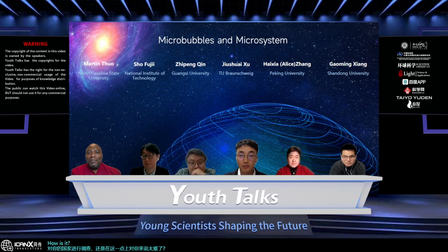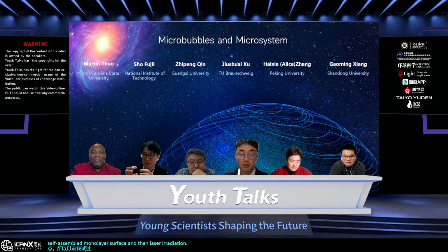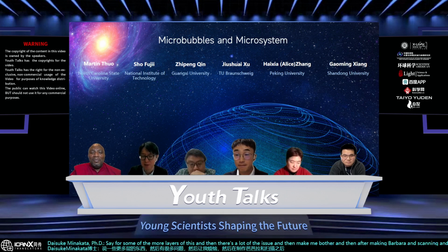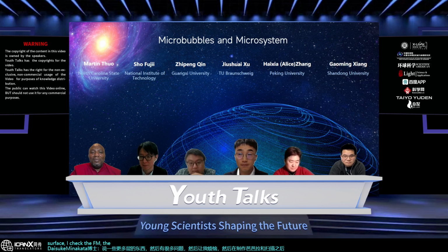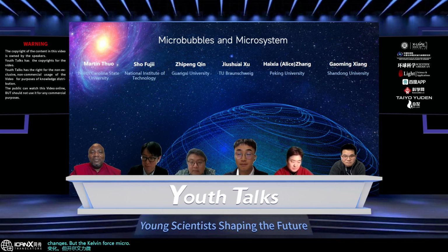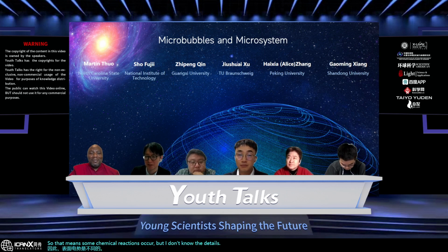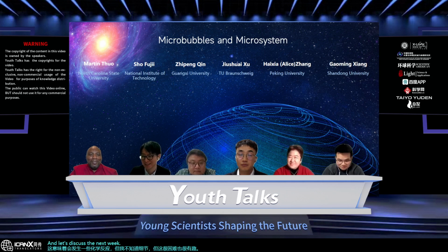It's a very good point. Previously I tried a self-assembled monolayer surface, then irradiation and making a bubble, and then after making the bubble and scanning the substrate surface, I checked with AFM and saw no topological changes. But with Kelvin force microscopy, the surface potential is different. So that means some chemical reaction occurred, but I don't know the details. It's difficult, but very interesting. Very good. Let's discuss next week. Yeah, we can talk about it next week.